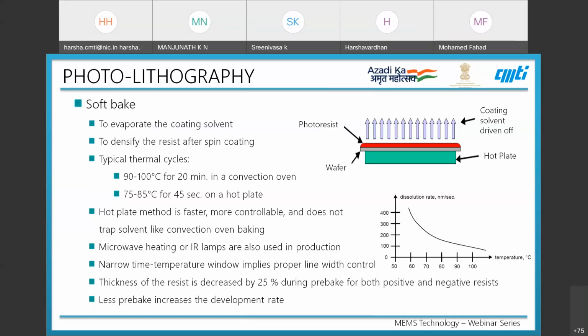As seen in the image, there is a hot plate which is placed, and there is a wafer over which the photoresist is coated. When we do a soft bake, the coating solvent is driven off from the surface.